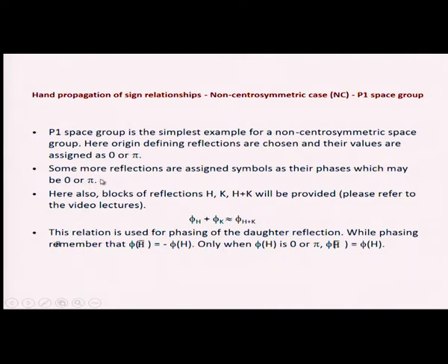In a separate lecture series, I will explain how to choose these origin defining reflections. Now, this is the formula we are going to use: phase of H reflection plus phase of K reflection is nearly equal to phase of H plus K reflection.